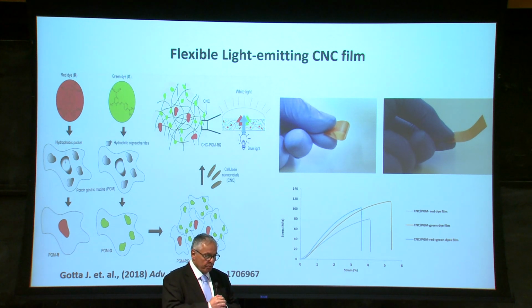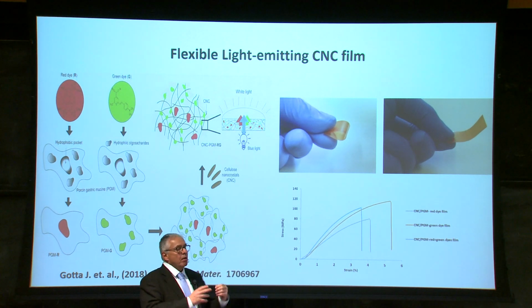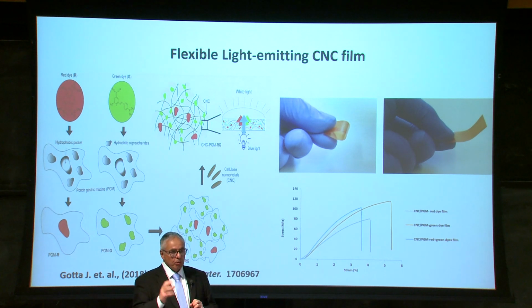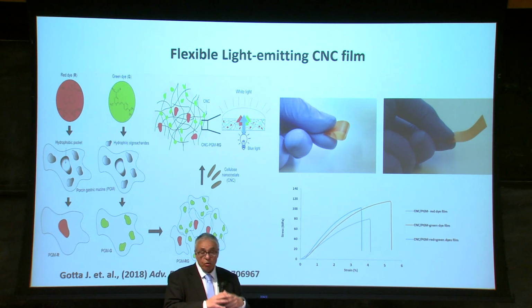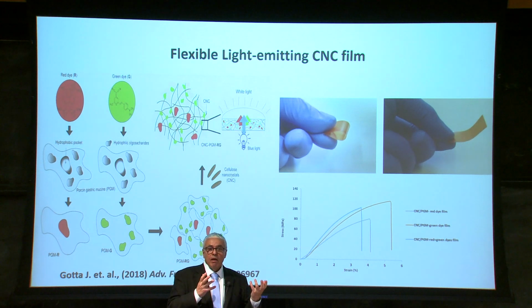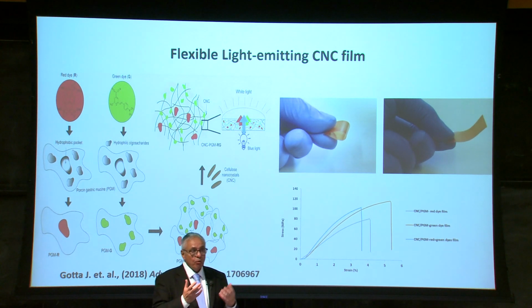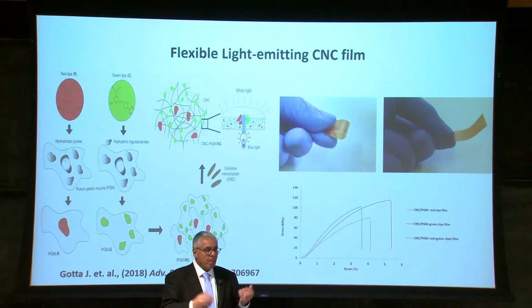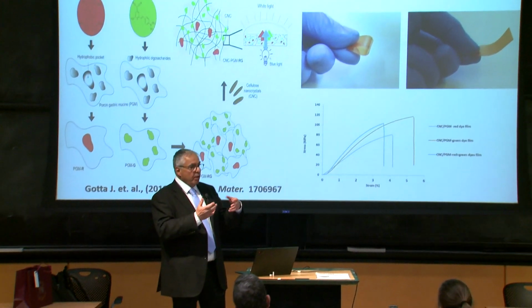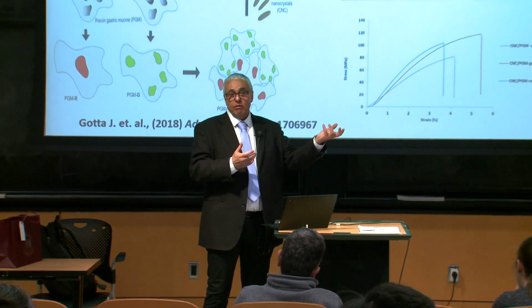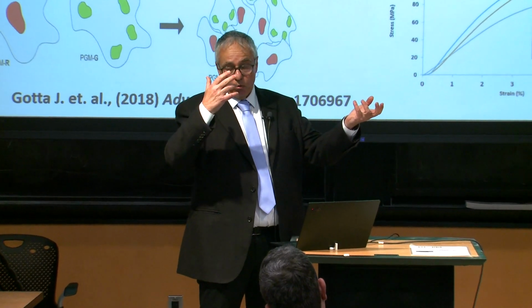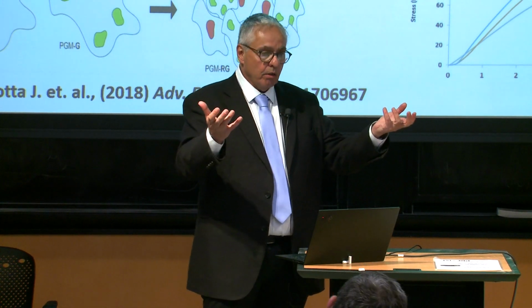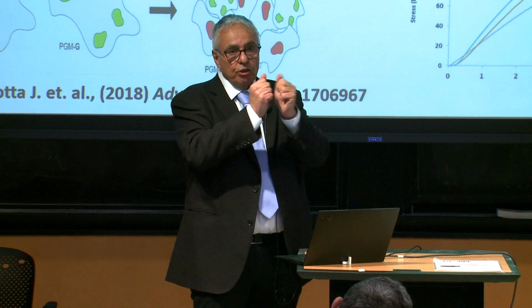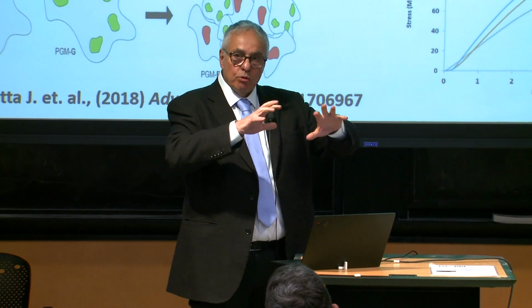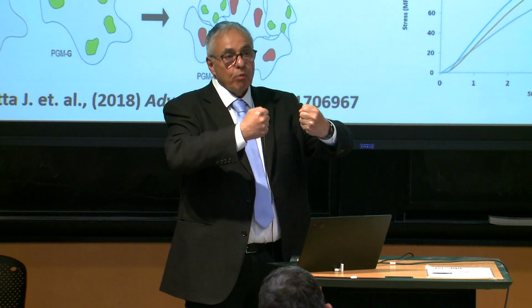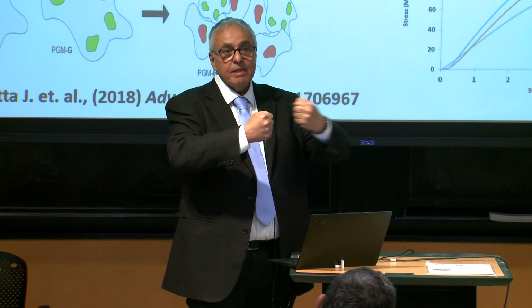So it's not reasonable. So what we've done here in this paper, we actually took another interesting biomaterial, which is called mucin. Mucin is a very interesting protein. They have both hydrophobic pockets and hydrophilic pockets. So if you mix them with either hydrophobic red color or hydrophilic green color, they will not bind to each other, but they will go to the different pockets. And by doing that, we actually prevent the problem of FRET. We want them to be separate.